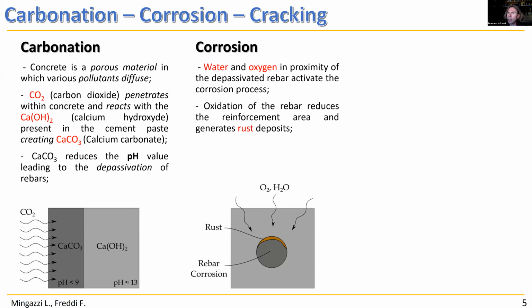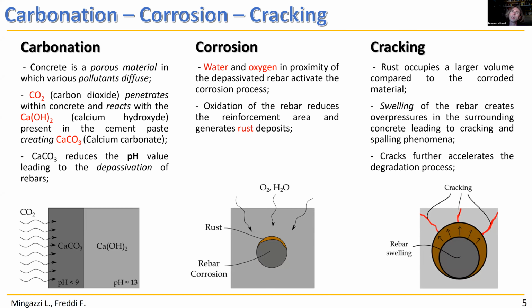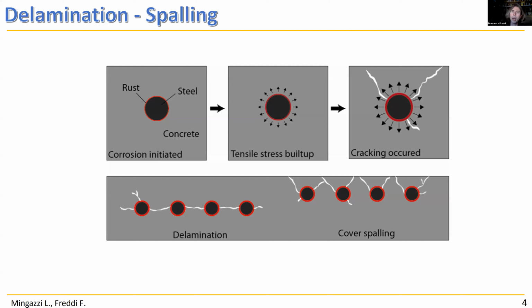There are two main effects: the reduction of the reinforcement area and the generation of rust deposits. The rust deposit occupies a larger volume than the integral material and the corroded material. So there is a swelling phenomenon that leads to overpressure in the concrete element, and at the same time tensile stresses in concrete that are extremely dangerous because concrete is extremely weak in tension. So cracks initiate and propagate within the concrete element, and this speeds up the carbonation process because there is a free way for CO2 to penetrate within the element. And these are the effects at the microscopic level within the concrete element. There may also appear some cover spalling or delamination that removes, in both cases, the concrete cover.